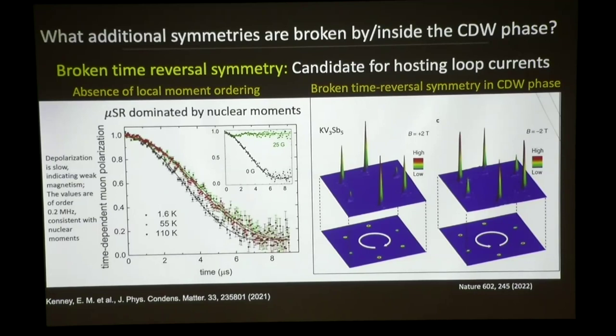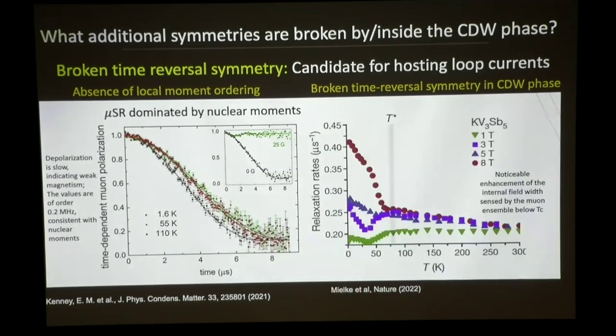And this was taken to be evidence for broken time reversal symmetry. So this is a system which has no local moments, and yet the charge density wave responds in a way that suggests that there's broken time reversal symmetry. That was followed by mu SR measurements in a magnetic field that showed that you have an enhanced relaxation rate below the charge density wave transition temperature. And this also indicates that the CDW breaks time reversal symmetry.